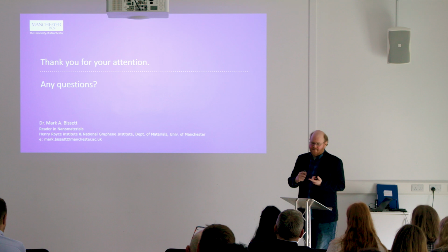Yeah, it's kind of a combination of things. The main thing is the morphology of the flakes. If you have very thin flakes, they're more easy to crumple, more easy to wrap around themselves, and the effective aspect ratio you get in a composite is less than when you look at the flakes as a powder by themselves, because they're too flexible, they roll up on themselves, and end up having a lower aspect ratio. So you want your flakes to be slightly thicker so that they're rigid and hold their shape. It also depends on the chemical functionality. You want them to have a strong interaction with the matrix, so that they don't want to stick to themselves, to avoid that agglomeration, so they can disperse nicely and the matrix can completely coat them to get those mechanical properties.